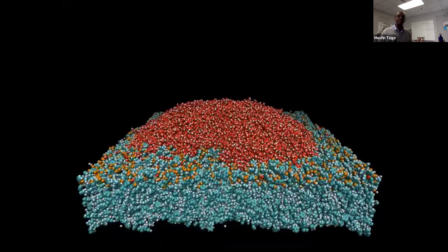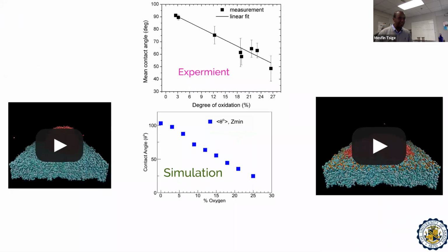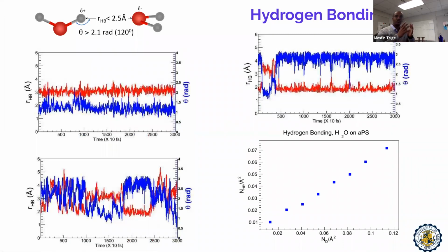The advantage with the simulation is that since we know the position and velocity of the atoms as a function of time, we should be able to determine several physical properties of the system. So the first thing that we have done is to look at hydrogen bonding. When this water droplet is spreading, in the case of oxidized polystyrene, they are forming and breaking hydrogen bonding with the substrate, as well as the hydrogen bonding with their own. The lifetime of hydrogen bonding of water is in the order of 20 picoseconds. They have a very short lifetime, but a broken hydrogen bond lifetime is even shorter, in the order of 2 picoseconds. So they form and break very quickly.